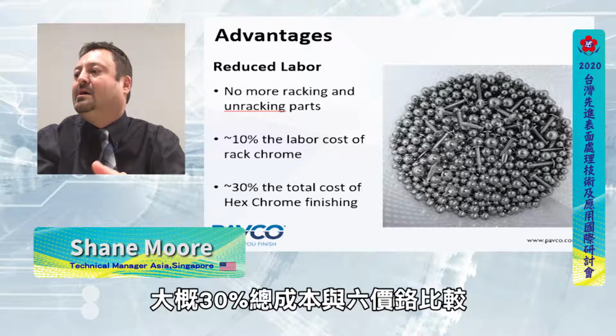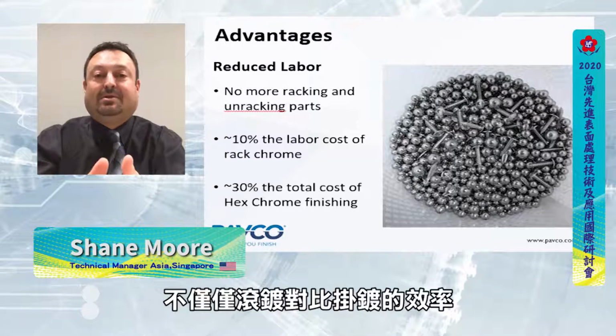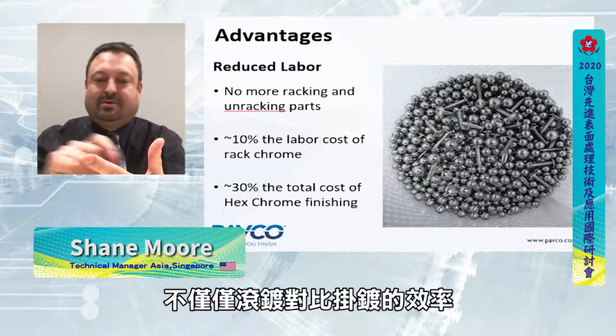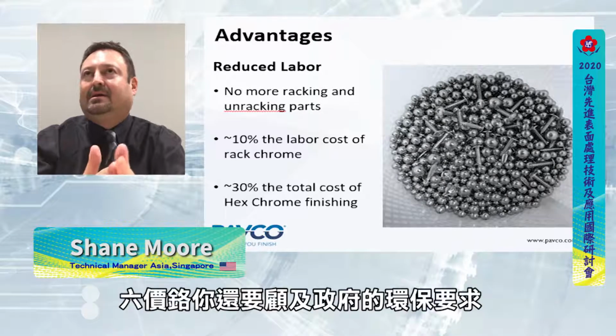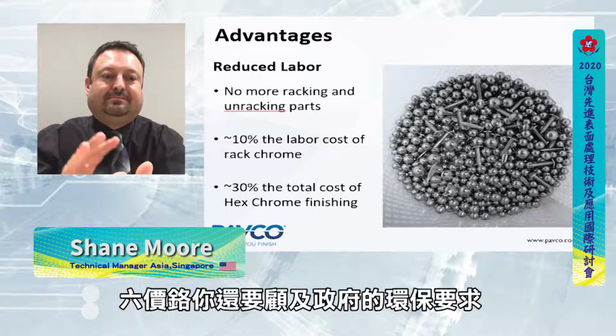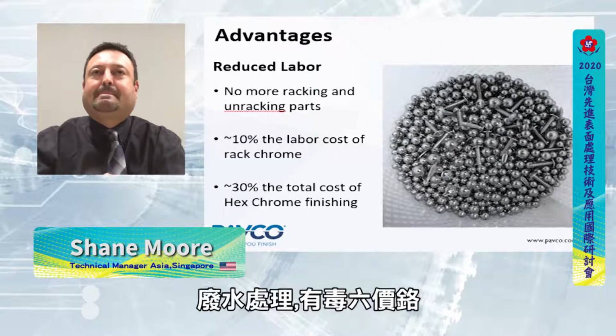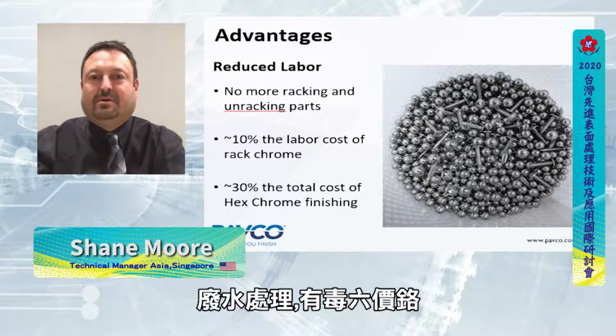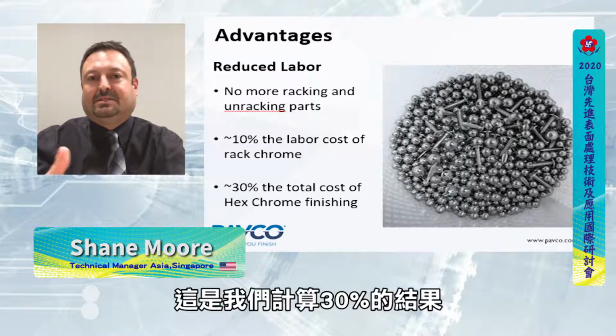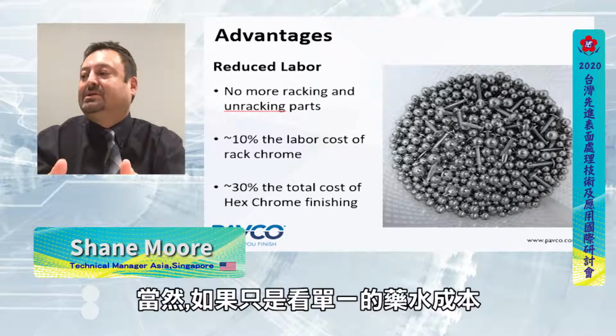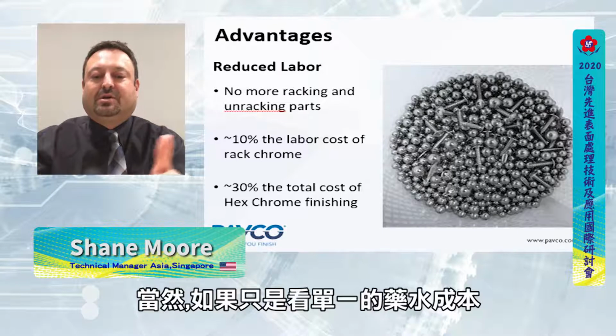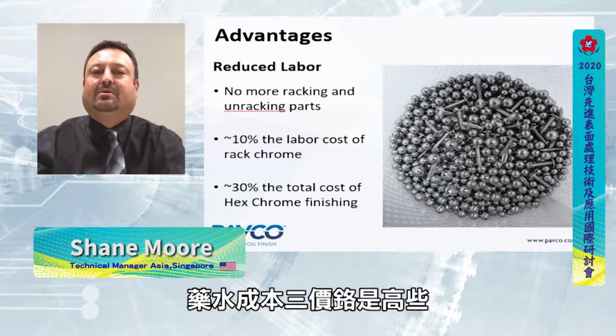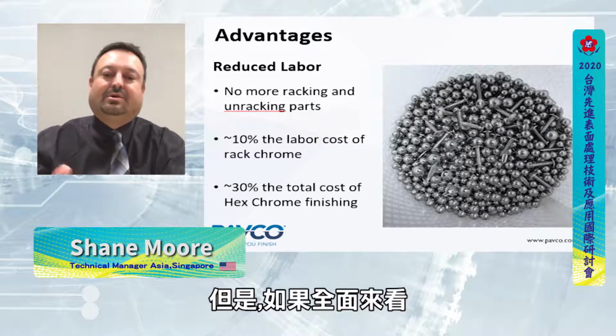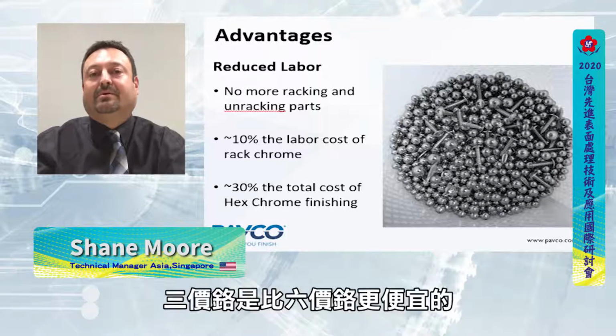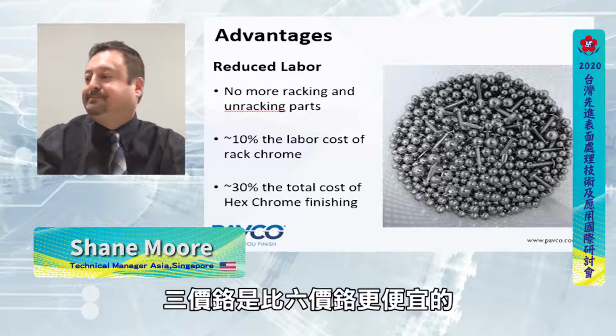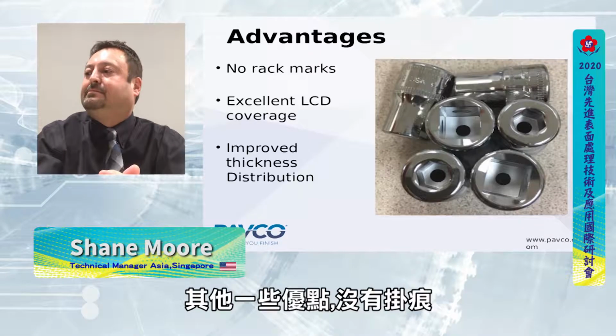Also, around 30% the total cost of hexavalent chromium. Not only can you plate it all in the barrel versus the inefficient racking. If you look at everything involved with hexavalent chromium, the governmental guidelines, the waste treating, the toxic effects of hexavalent chromium, if you put all of that together, that's how we came up with this, around 30% the cost of hex chrome, because this is really actually with any trivalent chromium. When you look at just the chemical costs, they are going to be a little higher than the hexavalent chromium. But when you look at all the other things that come along with the hexavalent chromium, it's actually cheaper to go with the trivalent chromium system. Much safer.